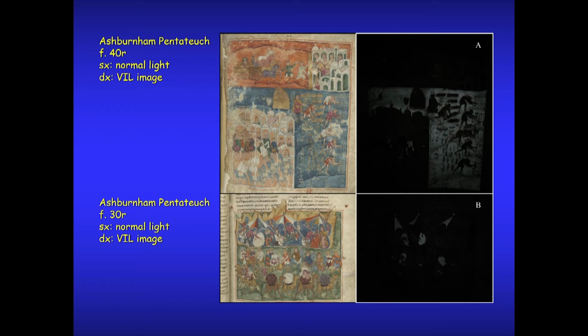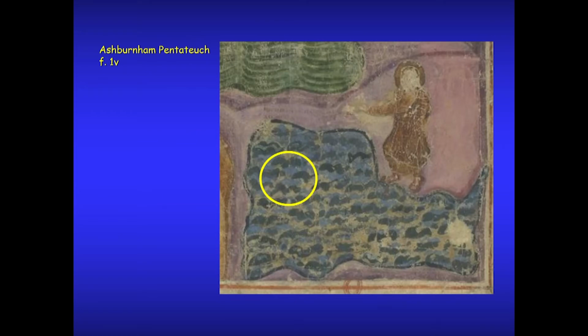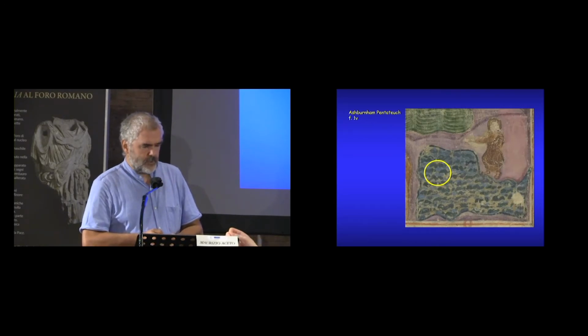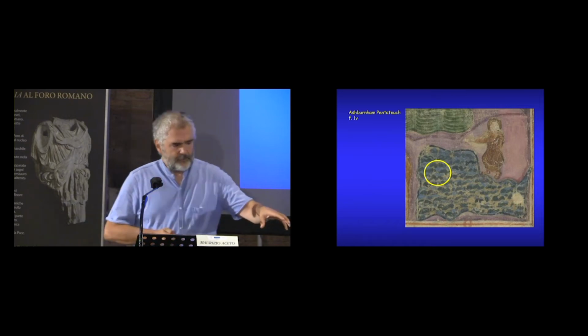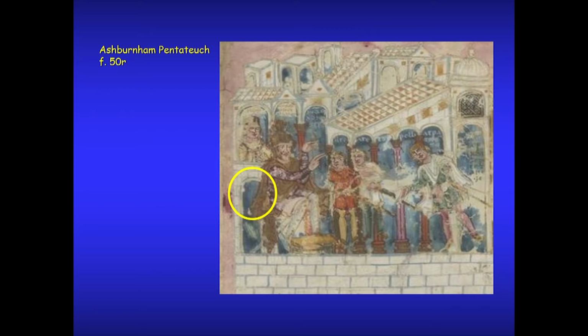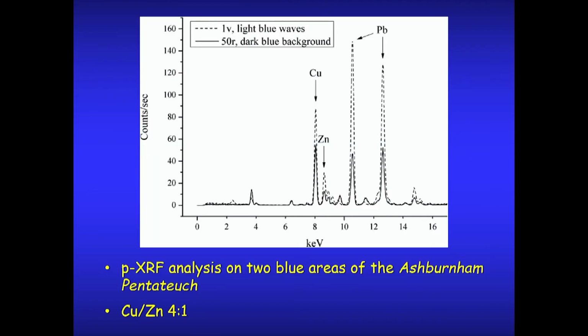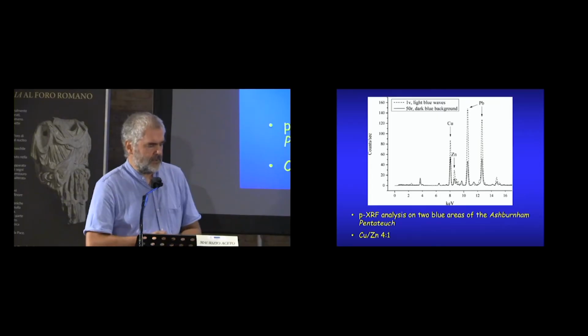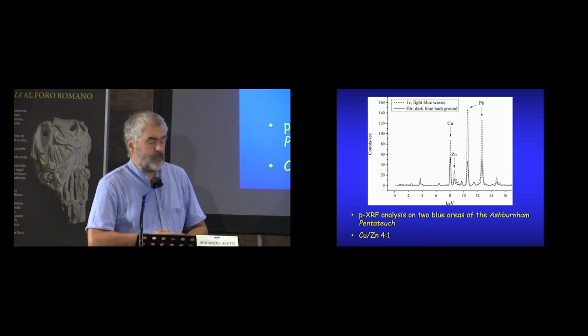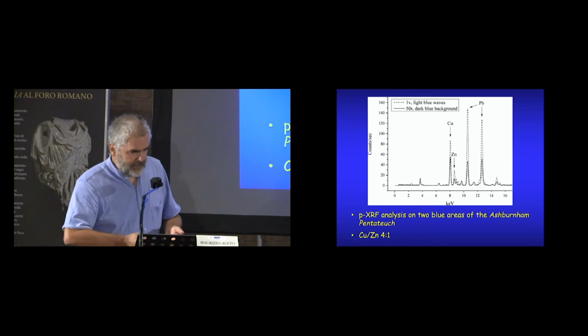There is a somewhat strange use of Egyptian blue, for example, for this background, as you can see, but also for some coats of, I can say, important figures. So this manuscript is unusual because Egyptian blue is the main blue pigment. This is very rare as far as manuscripts are concerned. And if you see the results of the XRF data, here you can see a light blue, and a dark blue, but the result is the same. Again, copper to zinc 4:1, exactly the same ratio among them, and the same as Castelseprio. Of course, the light blue has more lead because it's apparently mixed with lead white.